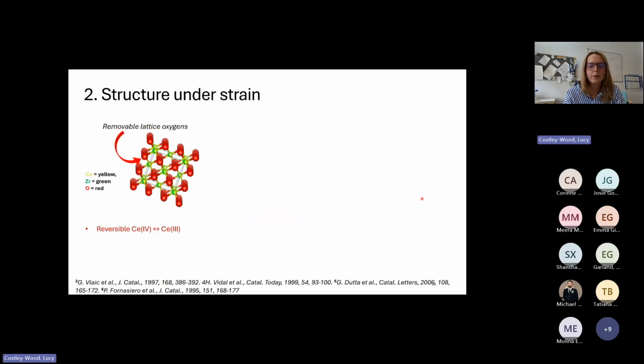So I've talked a lot about the removal of oxygen from the surface via the interface and how that correlates with the activity in the palladium redox. But thinking now about the actual bulk structure of ceria-zirconia and what happens to it during this. Well, I said that we can remove up to 25% of these oxygens. In pure ceria, without any zirconium there, you would only be able to remove around 10% of the oxygens.